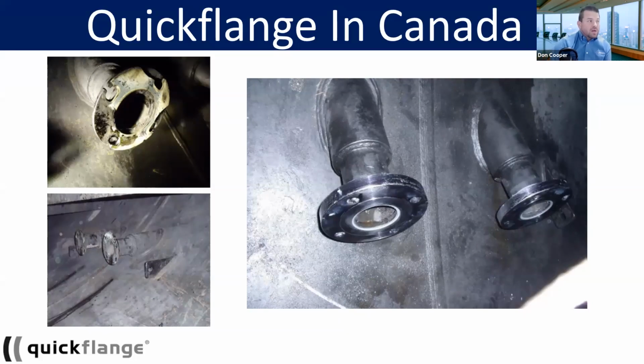We looked at this project, and this was before we had CRNs, but this project, because these flanges were inside the pressure envelope, didn't require CRNs. We were able to go into this vessel with cold work. We cold cut these flanges off, fit it. We removed and installed each flange in about 25 minutes. And the entire project to replace these 30 flanges was 2.5 shifts.